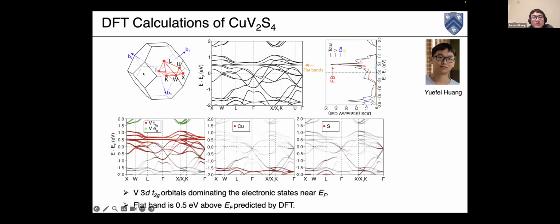And this is the DFT calculation for this compound. We really find that the low energy states are dominated by the vanadium states, where the copper states and the sulfur states sit at relatively higher binding energy, and they have some hybridization with these vanadium bands. And we also find a completely flat, or a very flat, three-dimensional flat band, but it is located about 0.5 eV above the Fermi level.